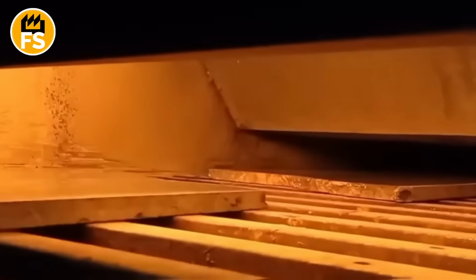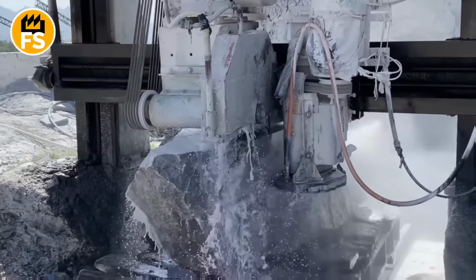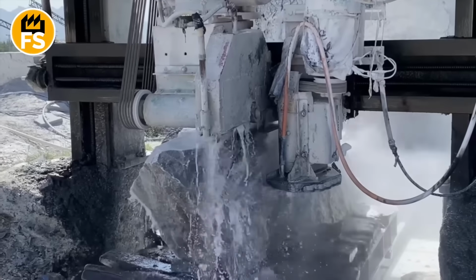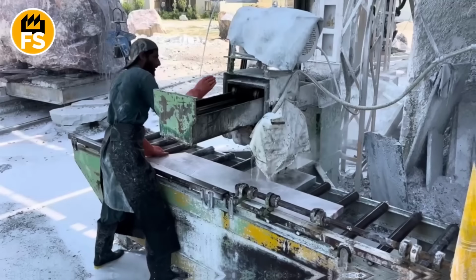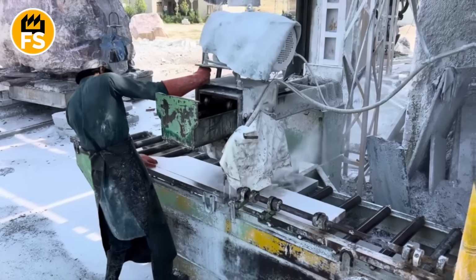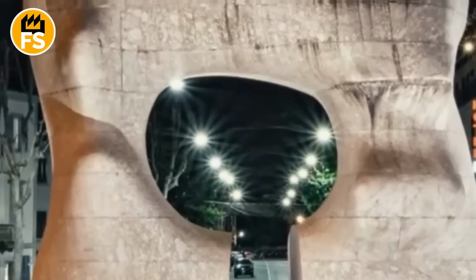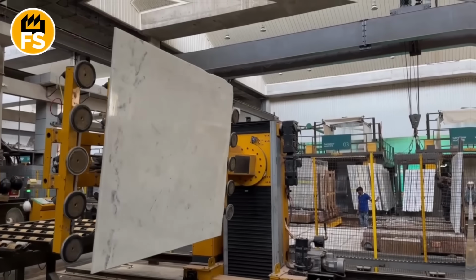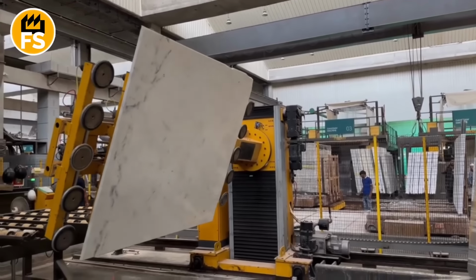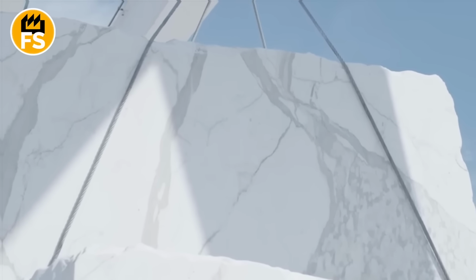Quarries are usually located in mountainous areas that are difficult to reach. To cut blocks weighing from 20 to 50 tons, expensive equipment is needed: diamond wires, cranes, hydraulic jacks. At the same time, about 30 or 40% of the quarried stone is suitable for commercial use. The rest is cracked or defective blocks that go to waste or are crushed into crumb. Due to the mass and fragility of the slabs, they are transported on special trailers or containers with cushioning. For imported marble, delivery can account for up to 30% of the final price.